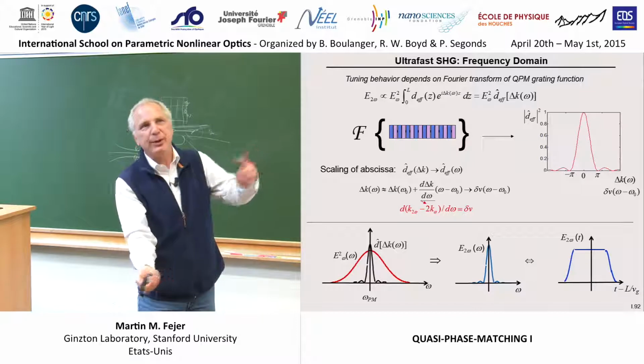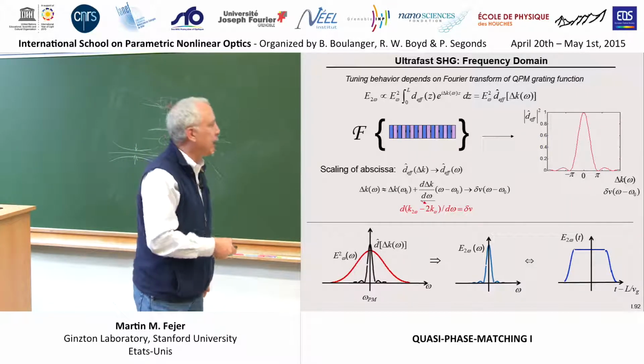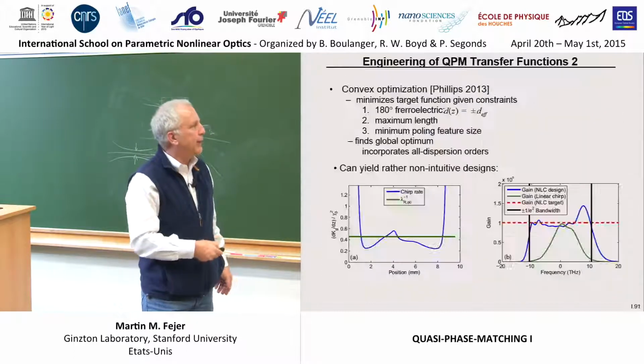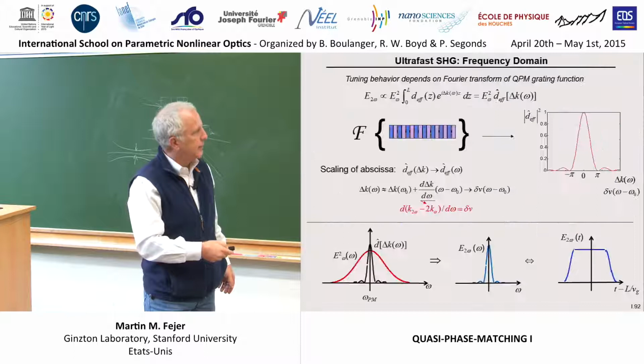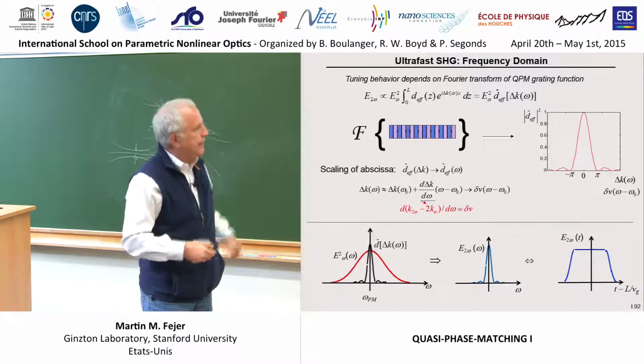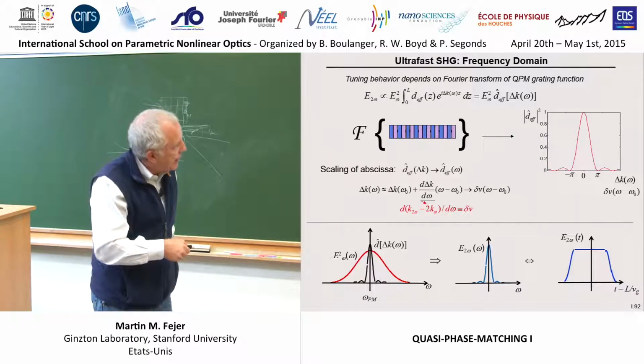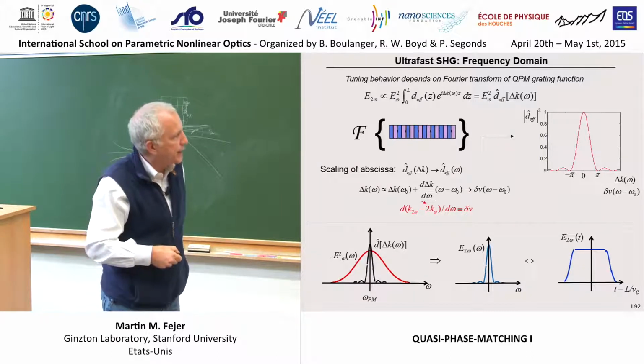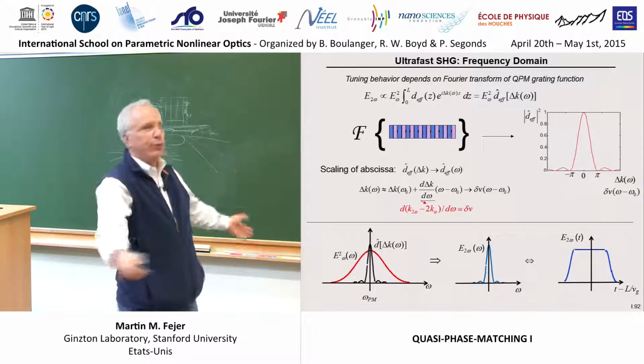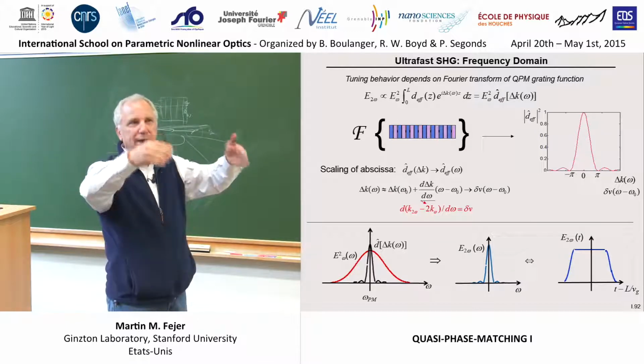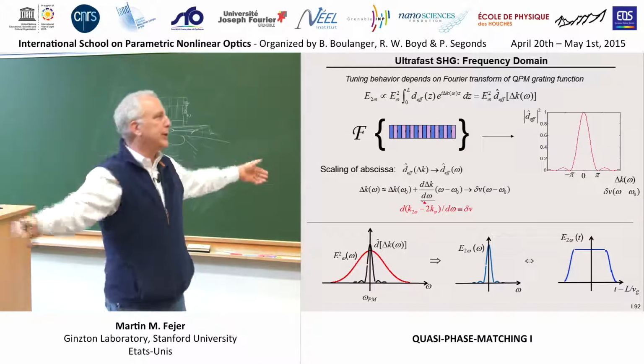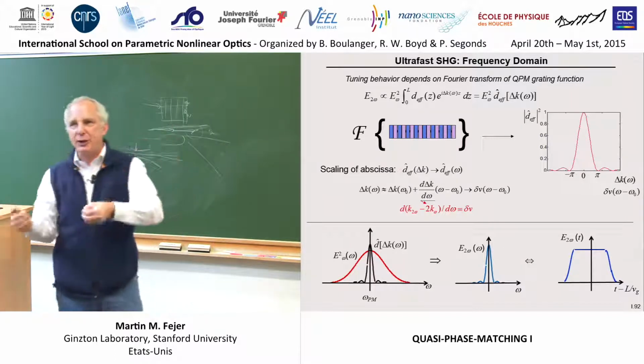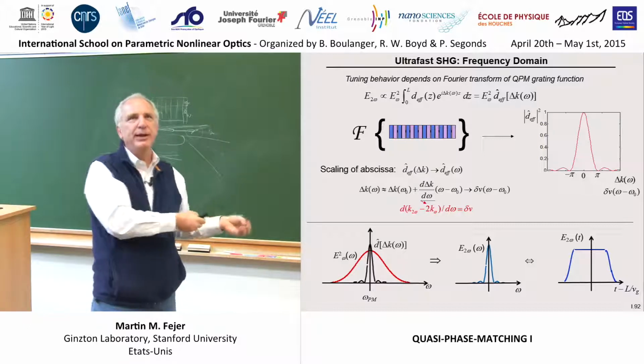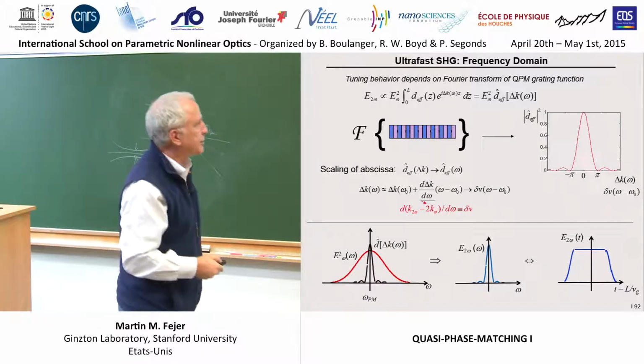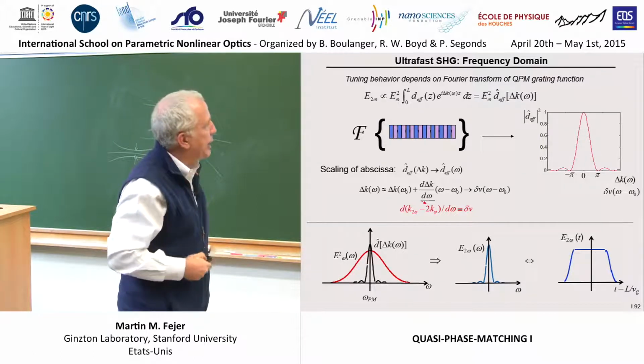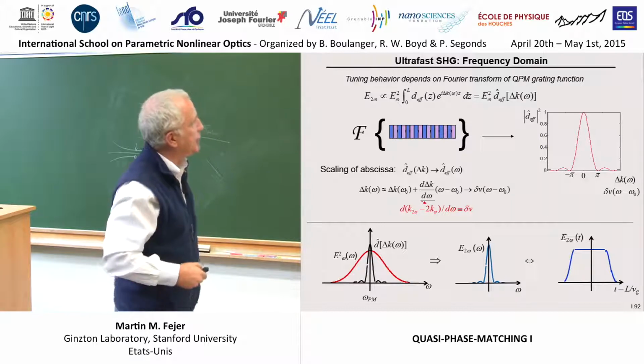So this is just a dual argument, whether you want to look in the frequency domain, it's a narrow band filter, reducing the spectral bandwidth of the harmonic and making a flat top. The longer the crystal is, the narrower this sinc function will be, the narrower the spectrum of the output, the longer the duration of the transform of that spectrum is. And that's just like the greater walk-off you get as your crystal is longer and longer. So there's an exact, not just an analogy, there's an exact correspondence. You can do this problem in the frequency domain, or you can do it in the time domain, however you prefer. And we will see that we can use this same Fourier argument and this same Fourier filtering story, even